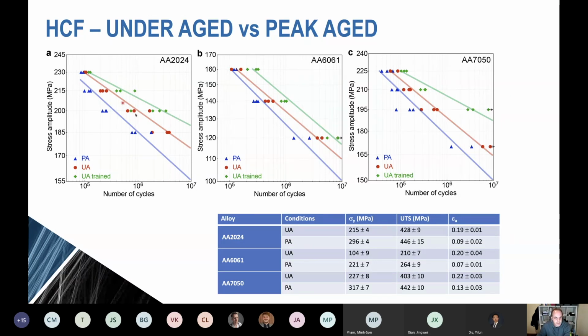And the blue and the red curves represent the peak age state and the underage state. So there's the SN curve for the peak age state for 2024, and the red curve is for the underage state. So we'll come back to the green curve in a moment. So consistently, the underaged material has better high cycle fatigue performance than the peak aged material. So the weaker material performs better in high cycle fatigue than the stronger peak age state. And so this is exactly the opposite of what would be expected, for example, from people working in the steel, where we see this very strong correlation between the fatigue strength and the UTS.